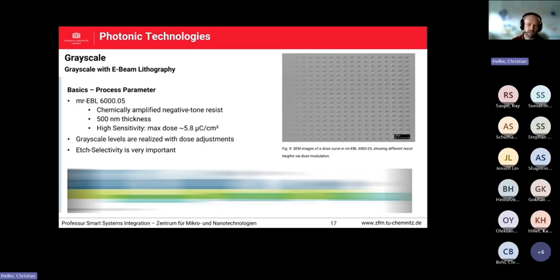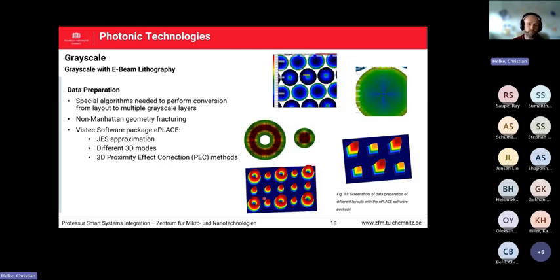So it's not done with just one wafer and one process. It's really process development based on the needs and specifications everybody has for the application or structure. And also one critical point is the data preparation itself. In the section before, I mentioned the proximity effect correction in 2D structures. You may think that it's also the case in 3D, and here it's much more complex because you also have the influence in Z direction. So this all has to be done with the data preparation to get all of these structures exposed.